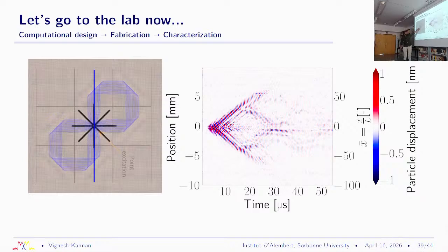Excitation is always at the center of this point, right? So here I have excitation, and you can very clearly see that the wave propagates. Here we did not do mirroring because you don't have any guarantee of symmetry. So this is actually experimental data collected throughout these positions and times, and you can see the wave excitation happening right here. In this case, we had our excitation at much lower intensities because we wanted to avoid killing the beams around the sample. So you can see that your amplitudes are restricted to about 1 to 5 nanometers.